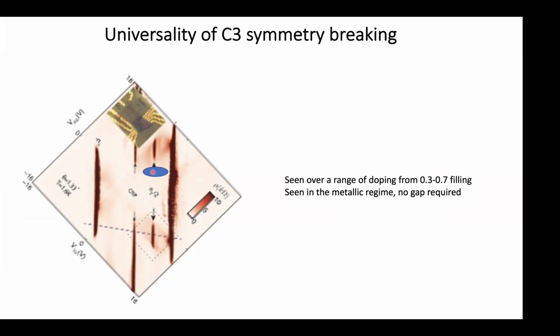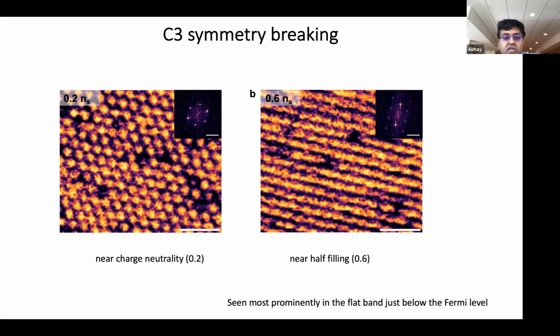So this is purely electronic, right? I mean, there's no distortion of lattice that you can see. Yeah, no distortion of lattice that we can see, and no evidence for any lattice distortion. But which direction is this nematic phase locked to? So it picks one of the three principal axis directions. And that's also evidence for the fact that it's an intrinsic phase. It doesn't pick some random direction. You can see here it picks this principal axis.